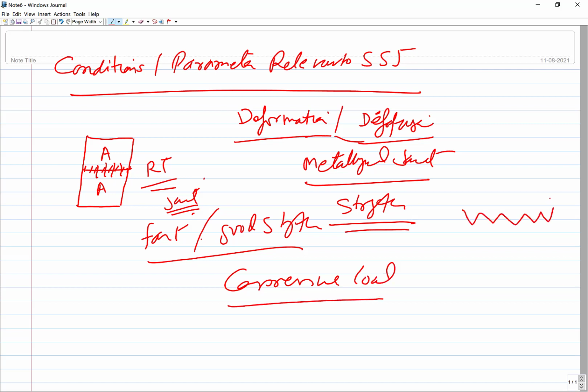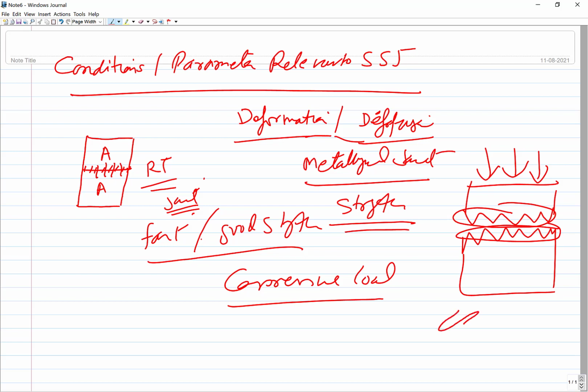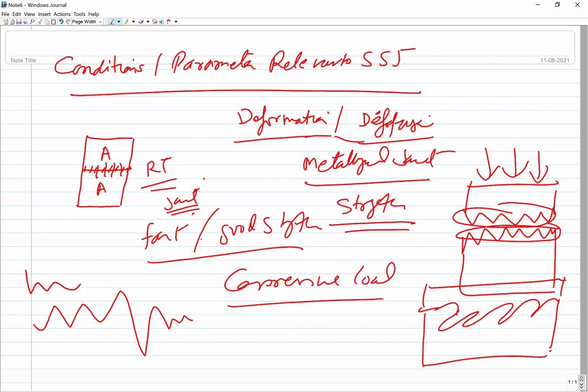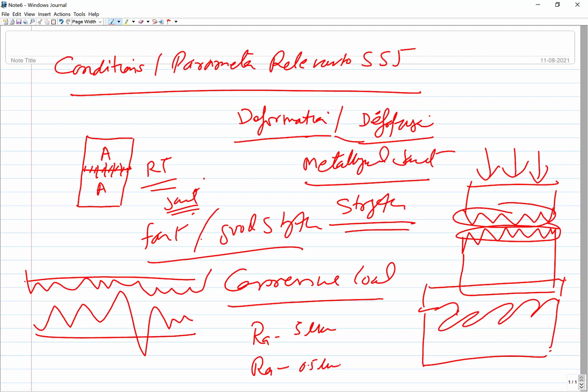Why compressive? Because whatever peaks and valleys are present on both sides of a component, only under compressive load can you make them collapse against each other, so that they form a kind of interface like this. The peaks and valleys have collapsed and come very close to each other; the surface may be rough like this on one side, and on the other side somewhat less rough. But when you apply higher load, these will collapse. This is one aspect. When you have a greater Ra, say 5 micrometer, or a smaller Ra, say 0.5 micrometer, in which case do you need more load to cause the surface layer deformation?